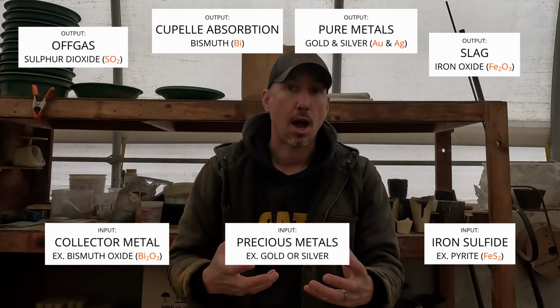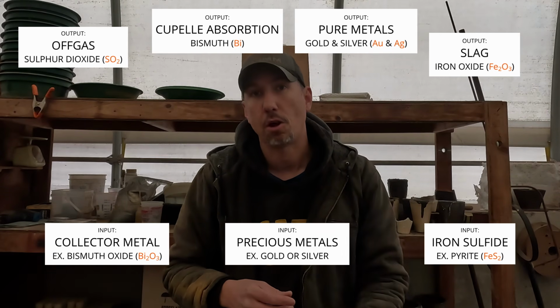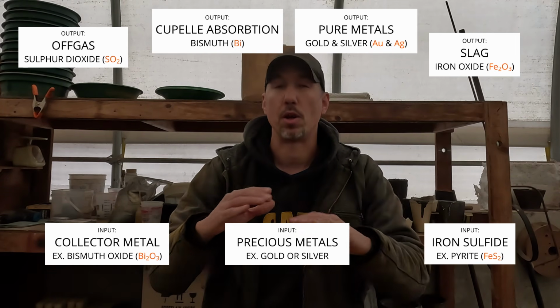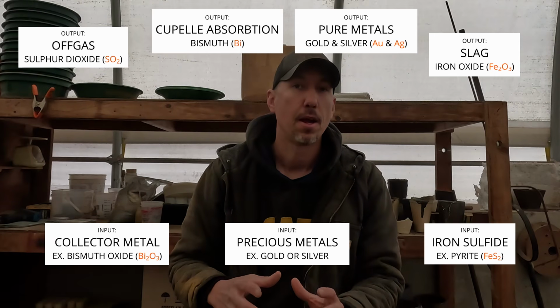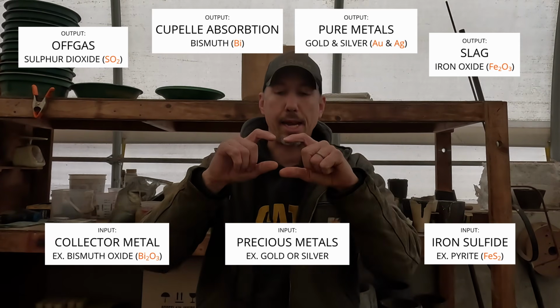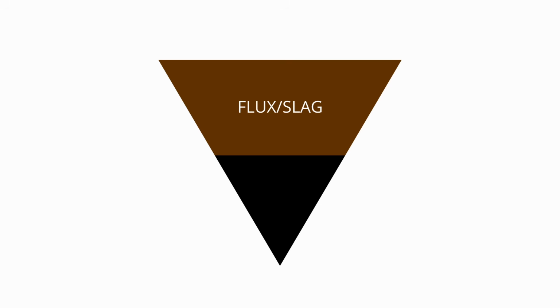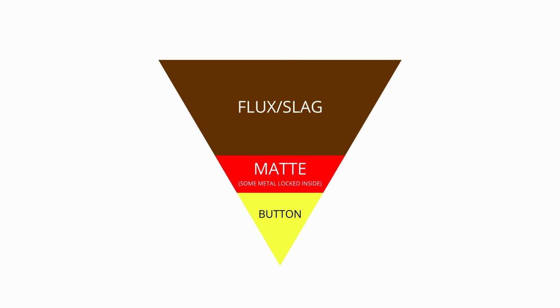So it acts as a little bit of an oxidizer and helps eliminate some of those sulfides that we're trying to get rid of. We do not want any sulfides in our smelt at the end because it ends up with a matte layer. So you'll have a flux layer, a slag layer on top. If there's any undecomposed sulfides, you'll have a matte layer, and then you'll have your metallic button on the bottom. If you have a matte layer in there, it's essentially a failed smelt. The matte layer can absorb precious metals, it can absorb bismuth, it can absorb lead, it can absorb all the things that you're trying to collect.